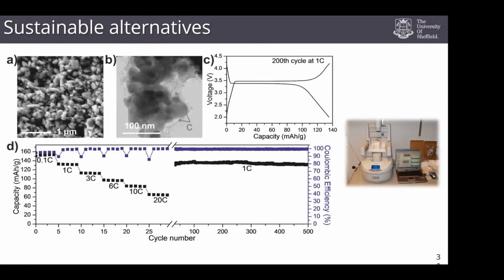We've made very small nanoparticles of lithium iron phosphate, which we then coat with a very, very thin carbon coating. Lithium iron phosphate is not very electronically conducting, so we add the carbon to improve the electronic conductivity. And what we find is that we get really great performance. And what do I mean by that? The theoretical capacity, if I was to calculate for all of those lithium ions to depart that lithium iron phosphate, would be 170 on this scale, milliamp hours per gram. We're getting close to 160 milliamp hours per gram for our materials.